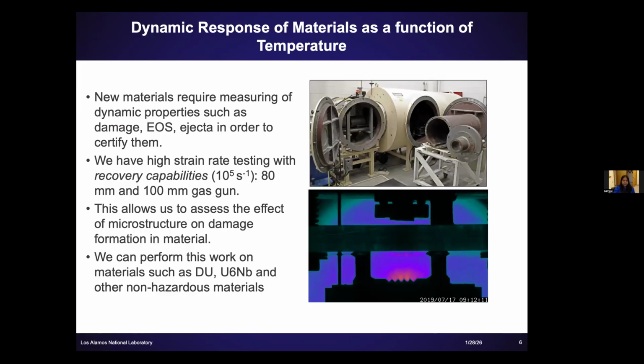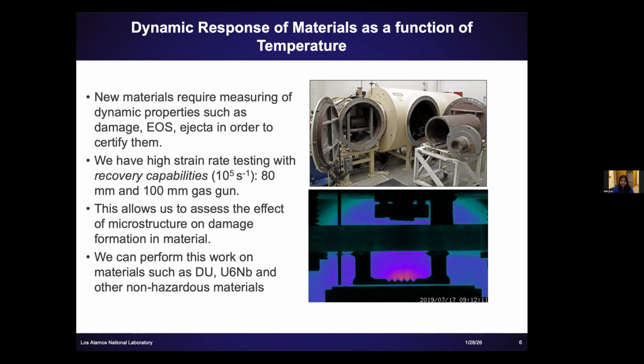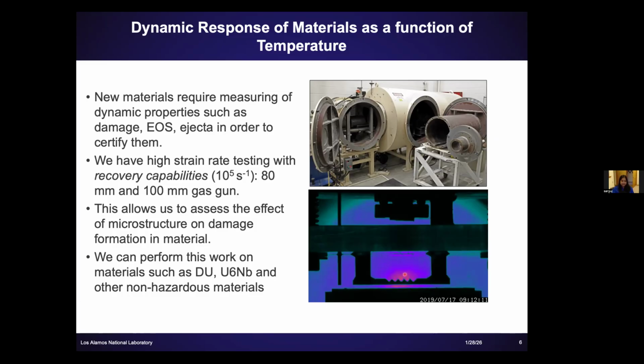And this is another part of our team where, in addition to our conventional mechanical testing on materials, we also do a lot of shock experiments on materials to parameterize, to measure the equation of state of materials, to look at how materials fail, especially as a function of the microstructure. We look at ejecta, that is material coming off the surface, which is shown in the bottom movie that is playing on my screen. Basically, what you saw was a demonstration where we had machined a very rough surface on a sample. The shock came from bottom to top, and we're doing some high-speed imaging to look at how those perturbations invert. Right here, you'll see them invert and cause material jets to be ejected from the material. That's part of the dynamic properties in materials.